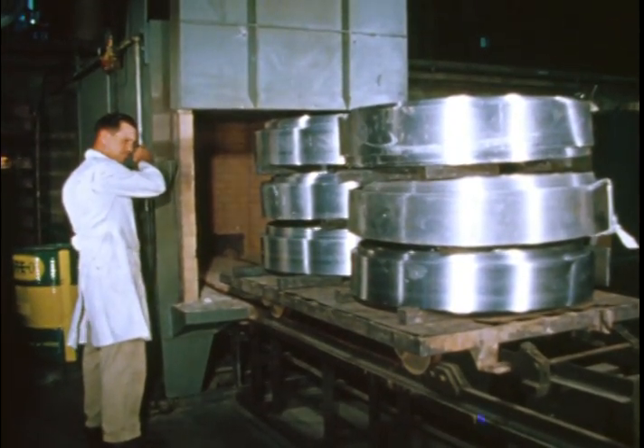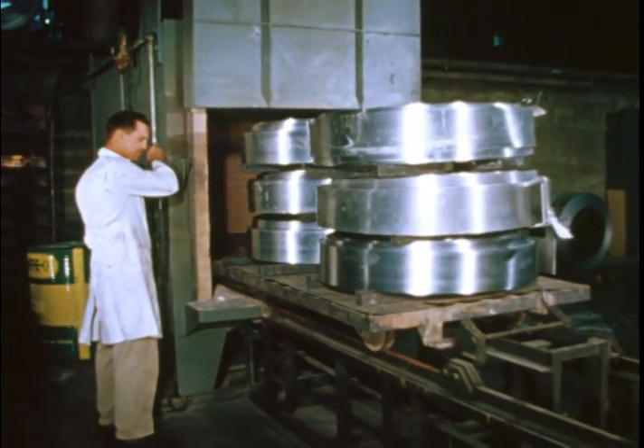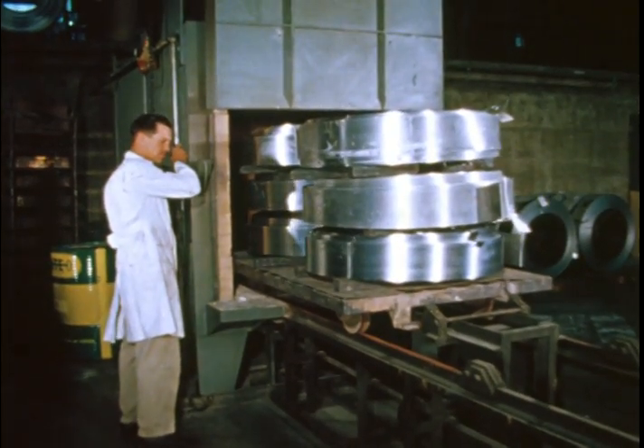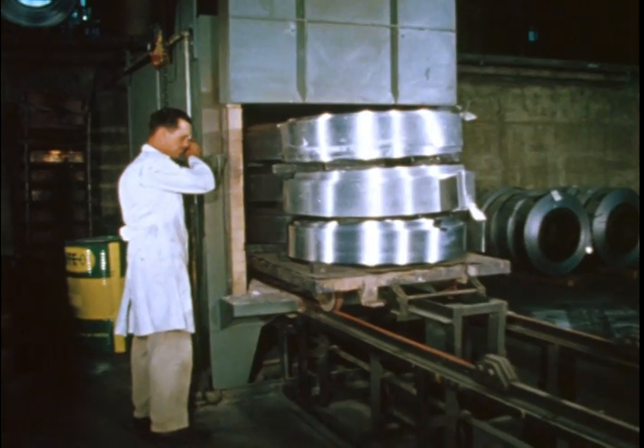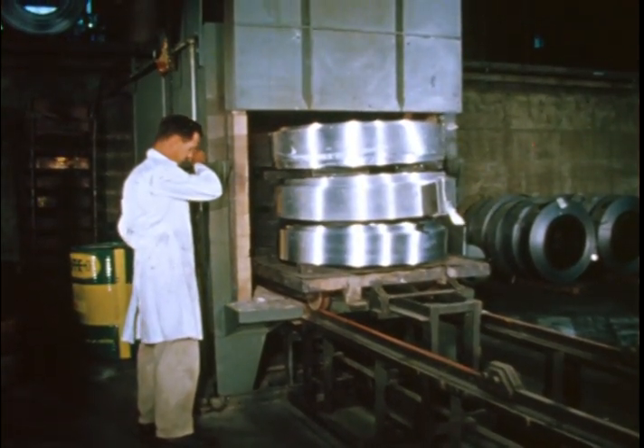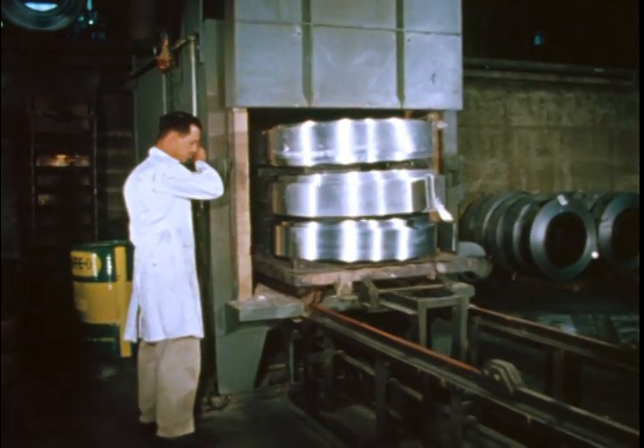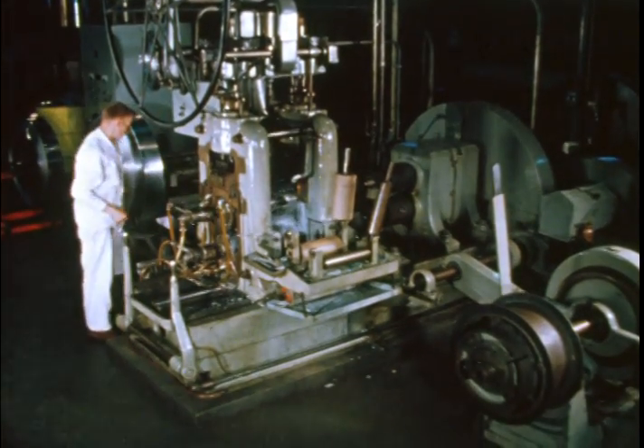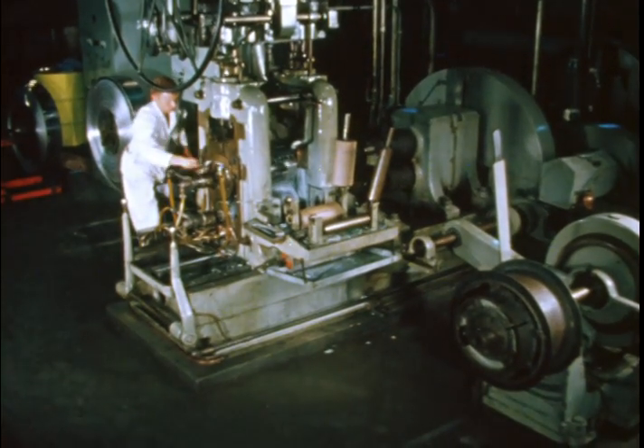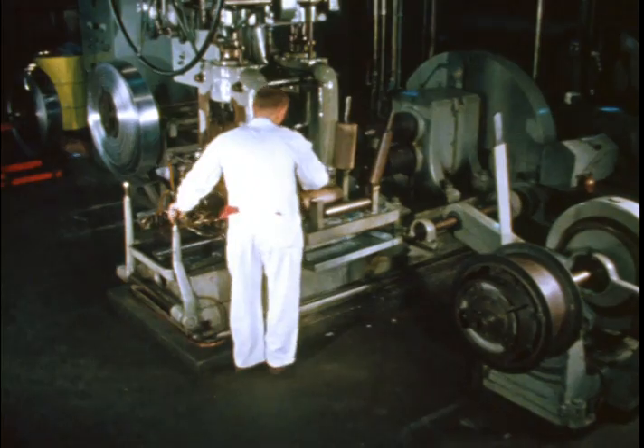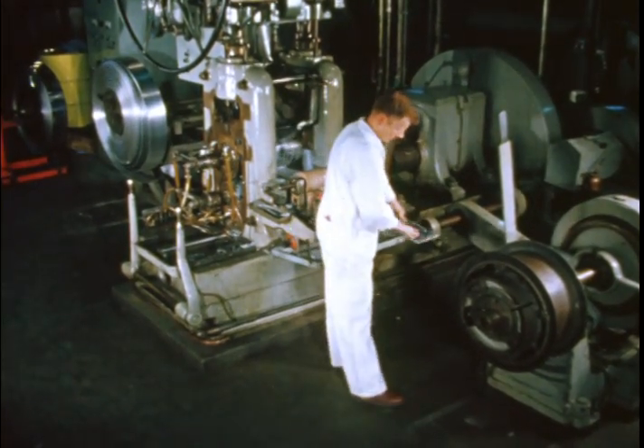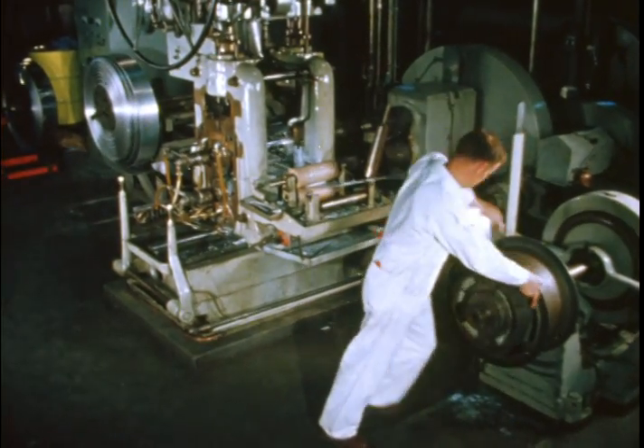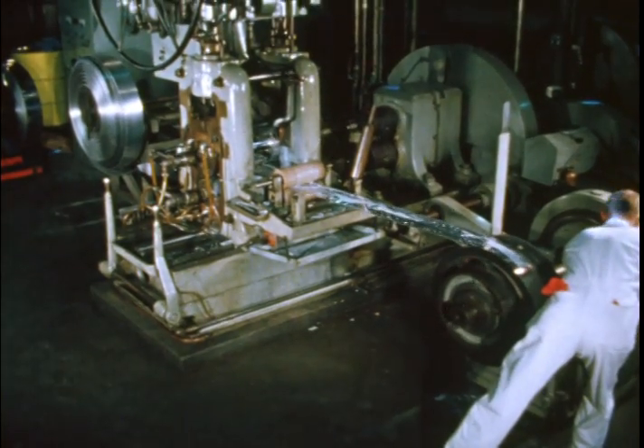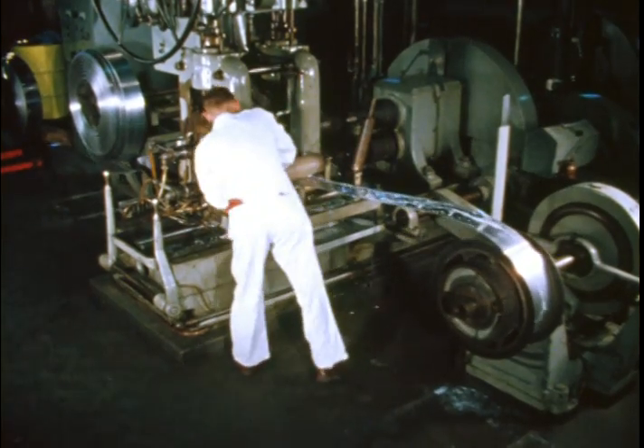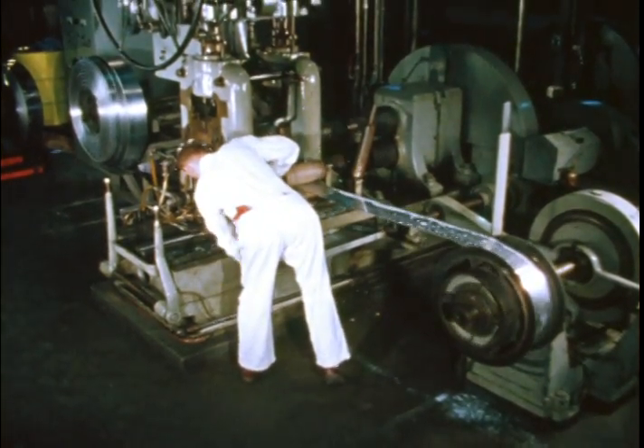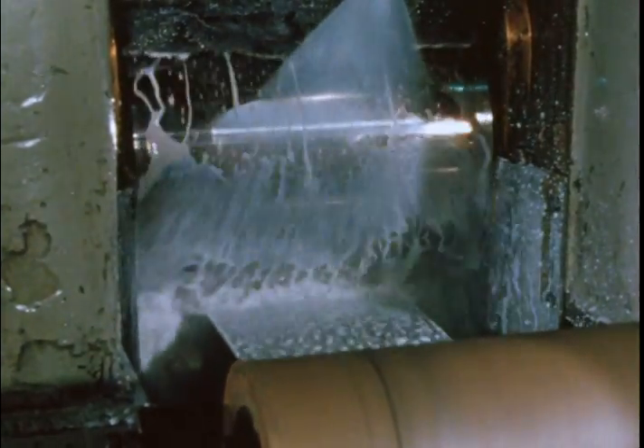The coils of lid strip also must be annealed before rolling down to lid gauge. The strip in these coils is of course 1/8 of an inch in thickness and must be rolled down to 14 thousandths in thickness before being stamped into lids. This is the strip rolling operation. Five passes through this mill are required to bring the strip down to gauge. And again you will note the milky rolling oil which is used to prevent sticking of the aluminum to the rolls.